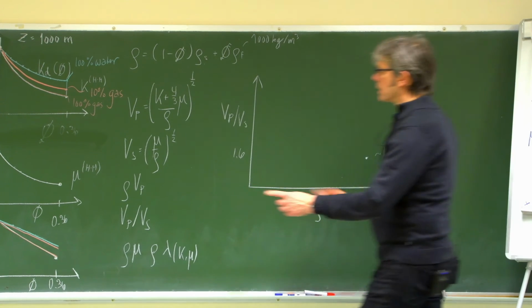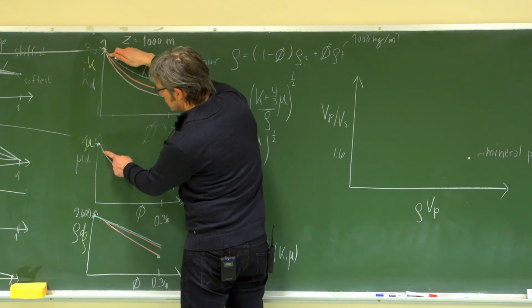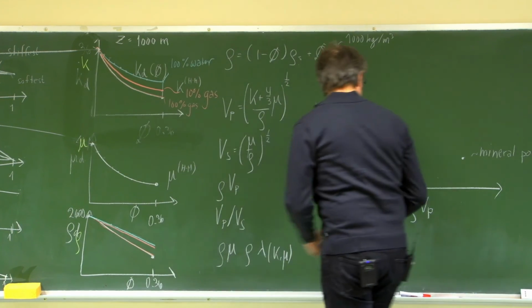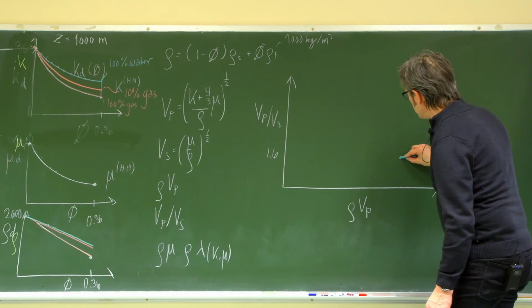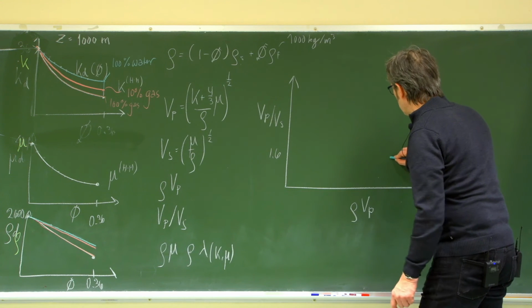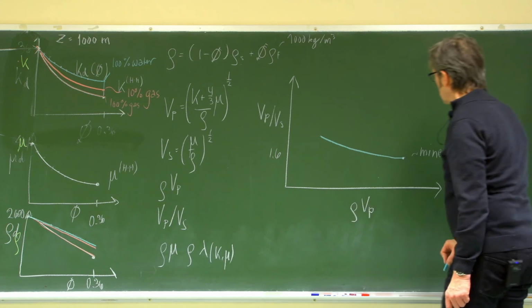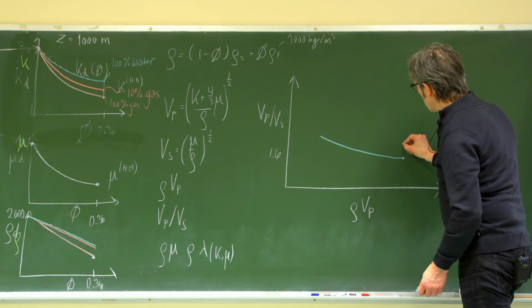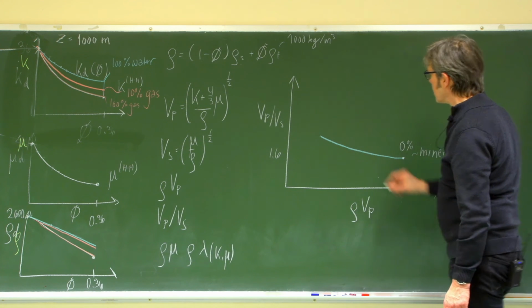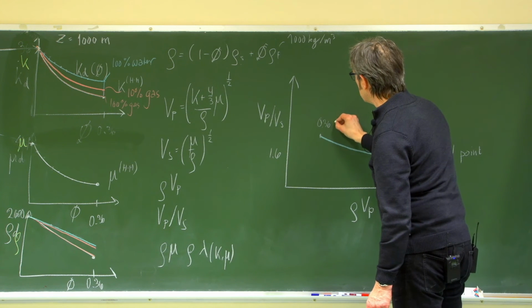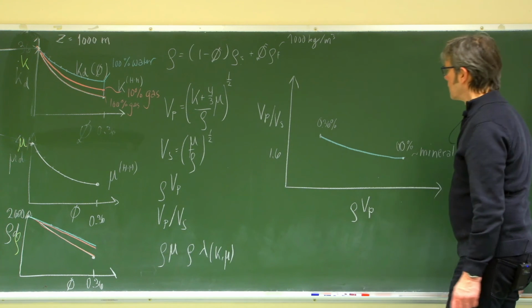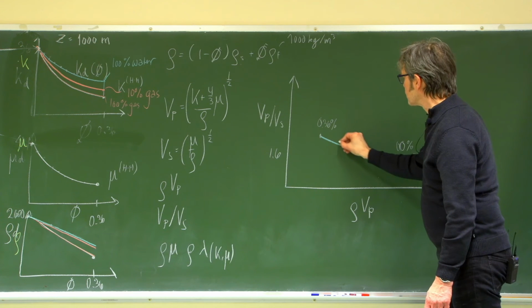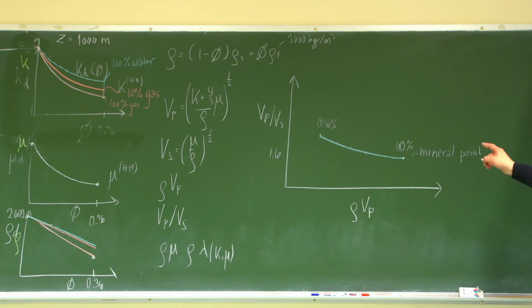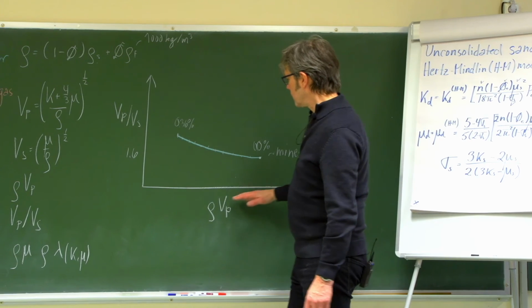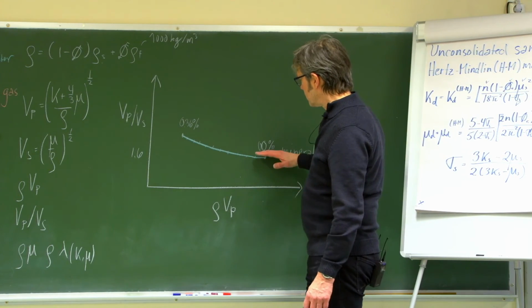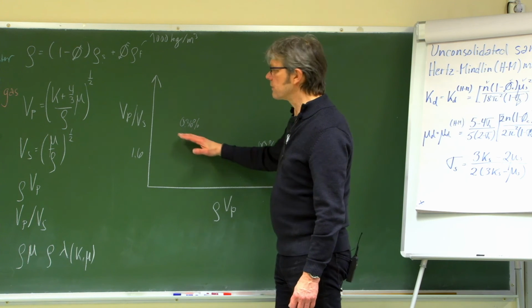Okay, so if I'm just taking that point, combining with that, and then the next one, and so forth, I would get this combination of the three lines, which would go something like that. So at this point I would have 0 porosity, and at the end point here I have 0.36 porosity. And then I have for each 5% maybe something like that. So that's the water. So we see that with the increase in porosity, clean sand, I would have maybe a slight increase in the Vp/Vs.